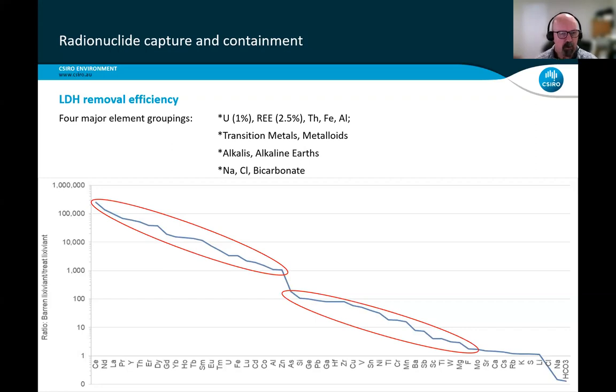The second natural grouping there is a whole lot of transition metals and metalloids. In fact, what I should do is just go back quickly and say that the concentration factors there for those rare earths, uranium and the like, anywhere between about 1,000 times and about 200,000 times. So the enormous removal efficiencies compared to the original barren lixiviant. We look now at the second grouping, and this contains predominantly transition metals and metalloids.